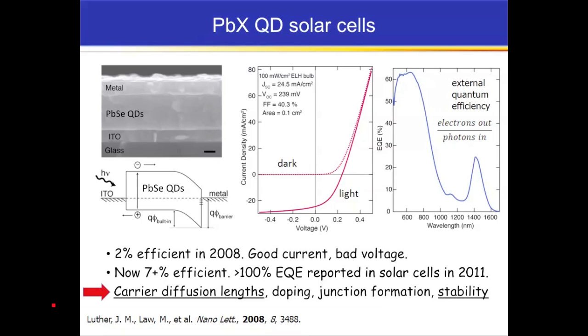It's a piece of glass with ITO on it, and then we have our lead selenide, in this case quantum dot film, and then a metal top contact. And this is something called a back contact Schottky device, where the electric field's at this metal semiconductor contact in the back. These initial devices were about 2% efficient, pretty high currents, so about 25 milliamps or so, very low voltages, about 0.2. If we fast forward to today, about 5 or 6 years later, we're talking about devices that, best in field, are about 7.5% efficiency.